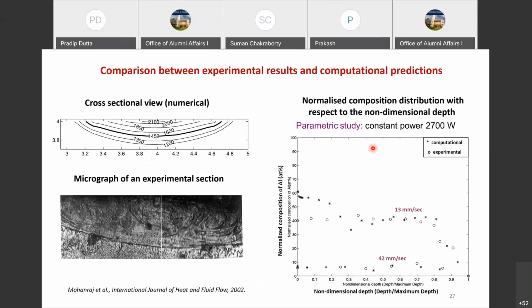Okay, now we compared with experiments also, looked at the clad layer and looked at the pool in the laser surface alloying. And it's a decent match, I would say, in terms of the depth of the pool. And then what we had predicted was the composition at the interface at the time of segregation. What we see over here, these circles are the experimental ones. On the x-axis, we have non-dimensional depth. So along the depth, we are just looking at one particular location, what is the normalized composition in terms of aluminum percentage.